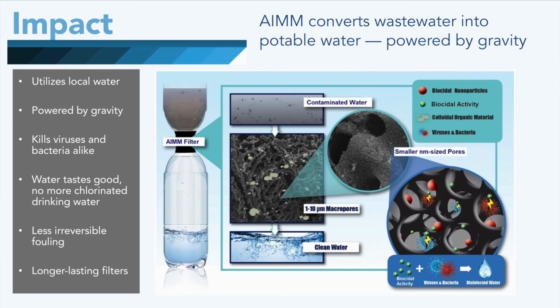These smaller pores also have silver nanoparticles embedded within their network of pores, which effectively kill viruses and bacteria. Additionally, there are sub-2 nanometer pores present throughout that capture taste and odor compounds, leaving the water actually tasting good instead of tasting like harsh chemicals. These multiple levels of vast porosity result in a highly permeable material with less irreversible fouling. This large porosity is present even with nanoparticles embedded within the pores.